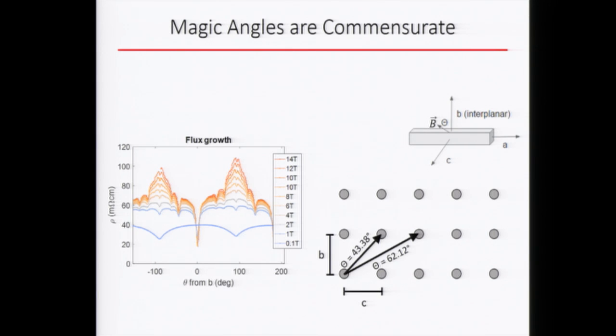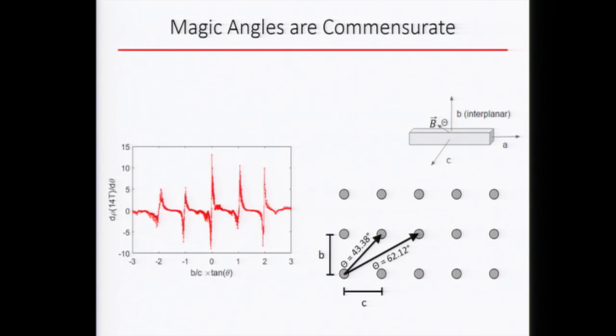This can also be seen by plotting the angle derivative of your magnetoresistance as a function of B over C multiplied by tangent theta. If this corresponds to the lattice constant, then it should be an integer. And indeed, you see peaks at every integer, although we only see 0, 1, 2.